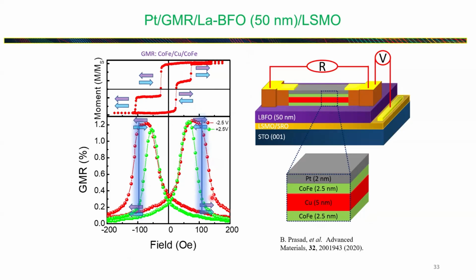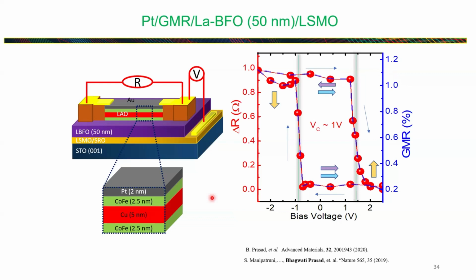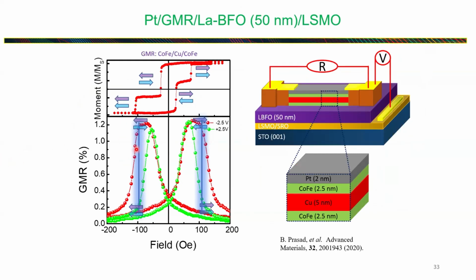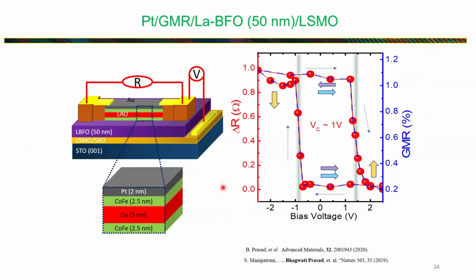And in fact, we can also achieve this state change from parallel to anti-parallel state of these two ferromagnetic layers just with the voltage. So you apply voltage, you can go from this state to that state. Okay, so this is just demonstrating that you can actually switch the GMR stack with the electric field. You don't need any magnetic field in this case, and you can get pretty much the same GMR percentage that you got here, around 1.2%. Okay, so you can achieve that without actually any magnetic field.